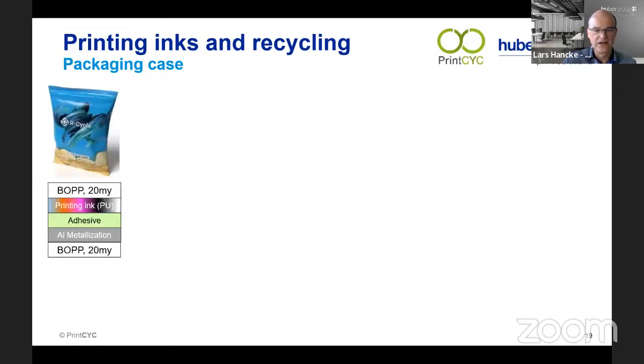Encouraged by these findings with the white printed film, we continued our journey and had a look at a real packaging case like you find it in many supermarkets. So we selected a crisp bag together with R-Cycle, a project for generating data to improve sortability of packaging waste. This is a setup based on a monomaterial polypropylene laminated against metallized polypropylene with a lamination adhesive recommended for recyclability, a 2K adhesive specially selected, and using polyurethane printing inks, four color set plus white.